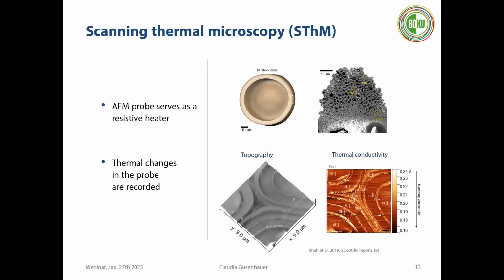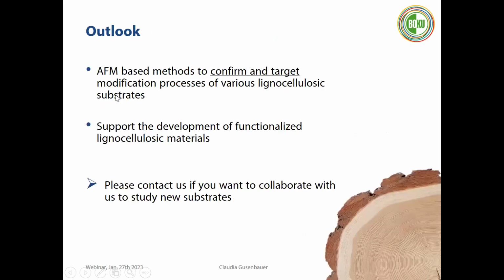And we can correlate this back to the different orientation of the fibrils inside each individual cell wall layer. So we have these further developments of AFM, and there's a lot of research going on in how to modify the AFM setup to not only get nanostructural information, but also to get information such as chemical distribution on a nanostructure, and also the nanothermal conductivity of our samples. We want to use these methods to confirm and target our modification processes. And we also think that this really helps the development of different functionalized lignin cellulosic materials.